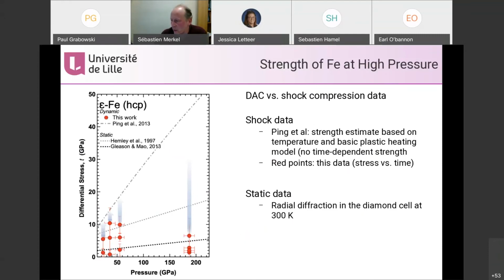You have the curves from diamond cell experiments here, which are quite low. And then you have this measurement of Ping et al. in 2013 from Livermore, where I want to point out that it's an estimate of stress which is based on temperature measurements. It's not a measurement of stress, it's a measurement of temperature increase, and then it's a model of plastic heating to reinvert the stress.